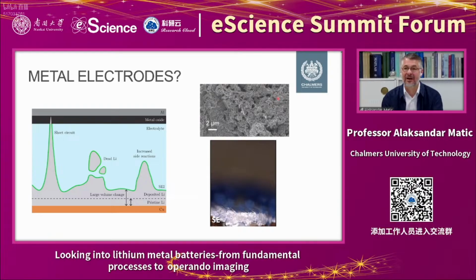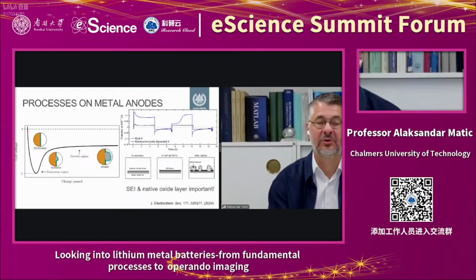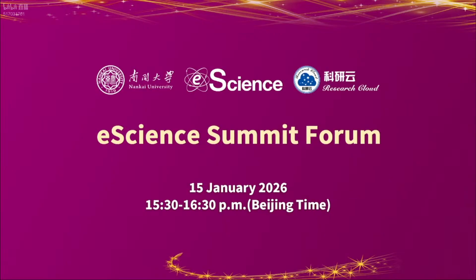And if you look at the processes from an electrochemical point of view, this is how it looks if you do a constant current experiment. Typically, the voltage curve initially drops fast below 0 volt, in this case we are depositing lithium. You have a nucleation region, which is signified by a peak. So you need a little bit of a driving voltage to initiate nucleation on a surface, and we'll come back to that. But before that, as soon as you start to pass a current through your cell, you always break down a little bit of your liquid electrolyte. So you are forming this SEI layer, the passivation layer, and it's below this that you actually then start to nucleate. And once you have nucleated, you can start to grow.